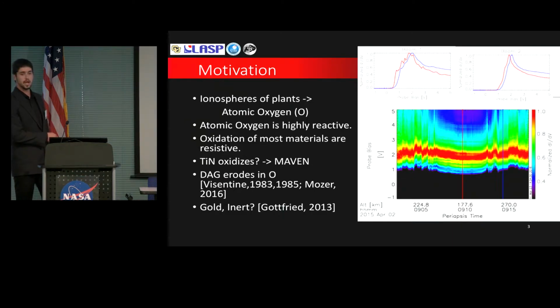The question then is whether or not the MAVEN probes did indeed experience oxidation, and what the general effect is of oxidation on the surface of a Langmuir probe. Additionally, MAVEN was using a titanium nitride coating, commonly thought to be relatively inert, at least at room temperature. There are other common coatings such as DAG and gold. DAG has been shown in previous experiments to erode over time in the presence of oxygen. And gold, while being inert at room temperature, has also been shown to degrade when bombarded by high energy oxygen atoms.